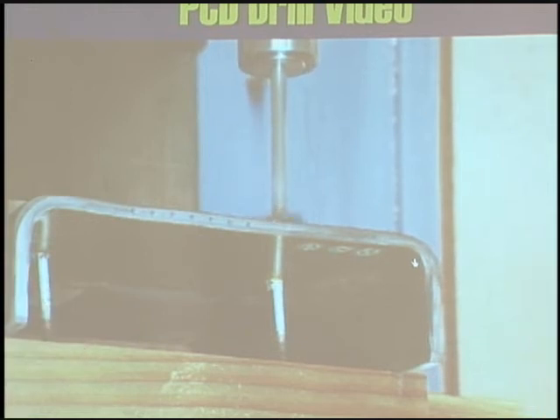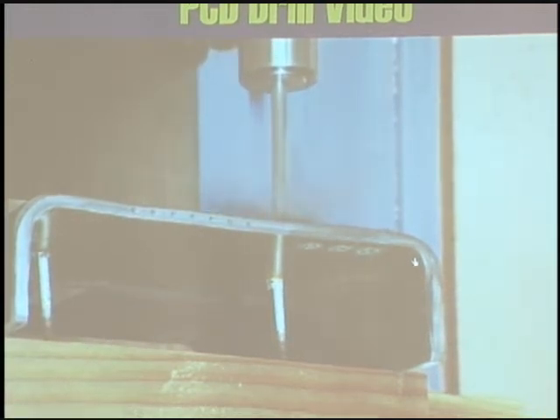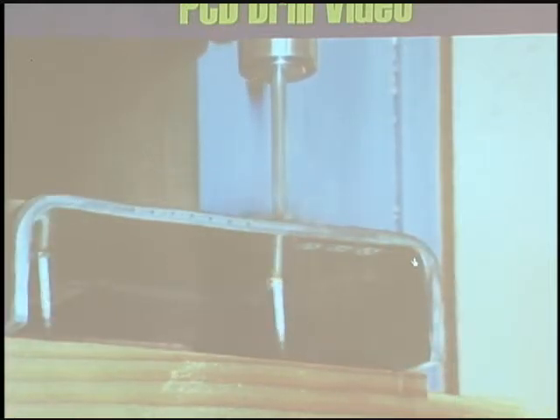So when we pass around that part, you'll see the exit holes. You're seeing some residue here, just the powder sticking to the material, but the part that's being passed through has had no secondary operations, no sanding, no deburring. That's the actual drilled hole that you're seeing.